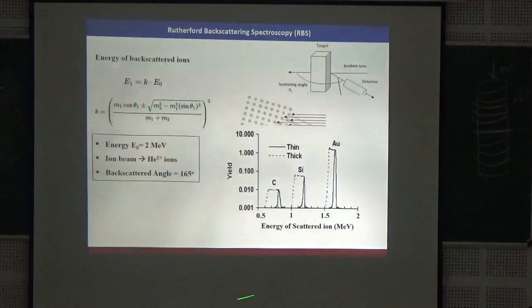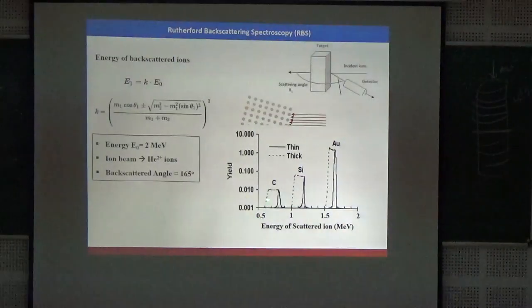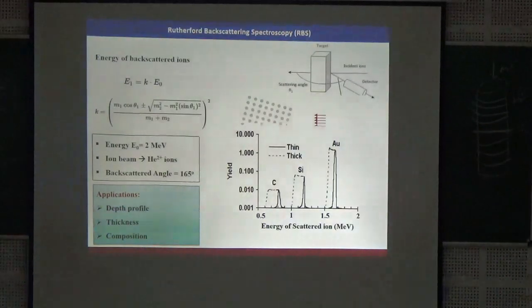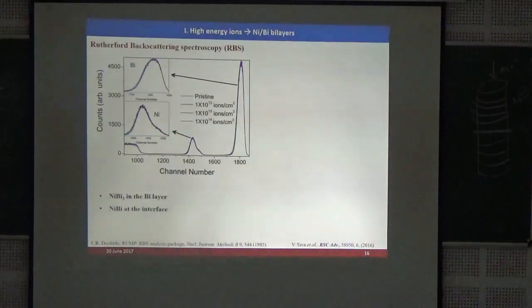So a typical RBS spectrum would look like this. The higher the atomic number, the higher the energy of the backscattered ions. Here you can see gold sitting at a higher energy, silicon at medium energy, and carbon at the lower energy side. If the thickness is more, then the distribution will be like this; otherwise it will be Gaussian in shape. One can get the depth profile and information on thickness and composition of the samples using RBS. Our RBS data would look like this for the crystalline and all the irradiated samples.